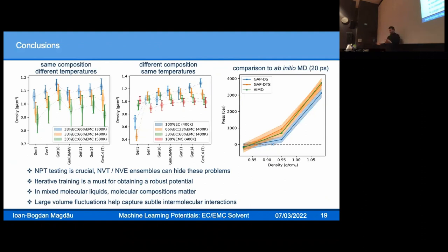Bringing it all together. All that we have learned has been put into the models. We find that all densities have converged across temperatures, across compositions. All densities are well reproducible at the same conditions. Just warm off the press, we got the result of our collaborators running ab initio for three months. This is an NVT simulation. We look at pressure fluctuations, done at three different volumes, and extrapolate the pressures to find the density at zero pressure. This agrees very well with our best GAP model.